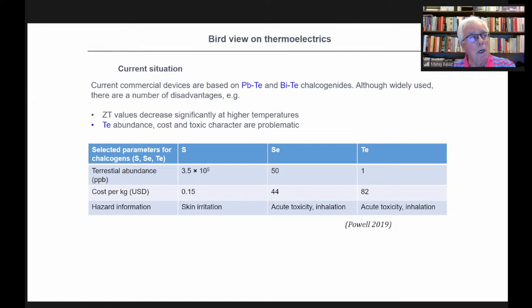One more remark. So how is the current situation? All these thermoelectric modules are composed of alloys of lead telluride and bismuth telluride, these chalcogenides. Although widely used, they have a number of disadvantages. Here are named two of them. The value of ZT, or figure of merit, decreases significantly at high temperature. So at high temperature, they don't work very well. And there is a problem with tellurium alone, because of the abundance, cost, and toxic character of this element.